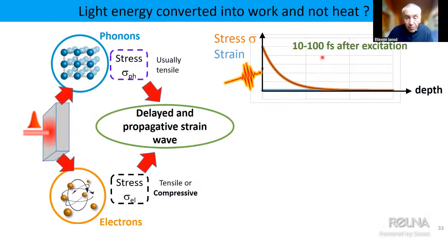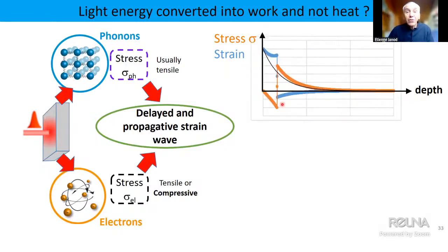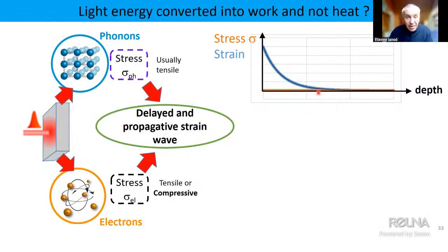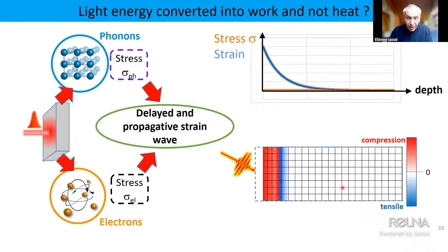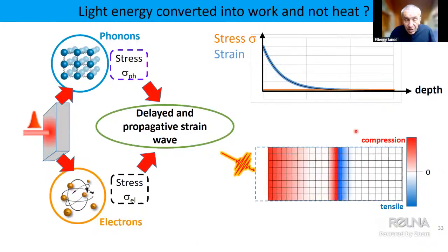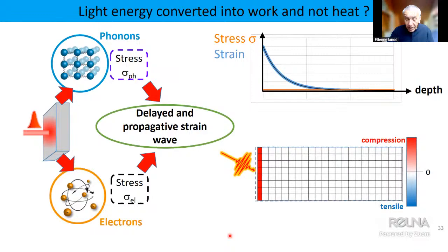After a few tens of femtoseconds, you have creation of this stress, and the profile of stress corresponds to the penetration depth of light. This is the surface of the material, and when you go to the right, you go to the core of the material. And then we have launching of a strain wave starting from the surface. You see that the surface deforms first, and here this is the front of the strain wave propagating, and this is what happens with time. At the end, the stress is now zero, but we have a constant strain that might stay like this during a few tens or hundreds of picoseconds. If I do a full image, it might be like this in the case of a compressive strain wave.